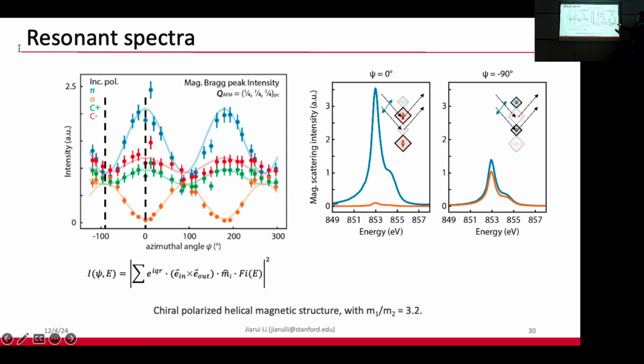So for example, at this position with a pi polarization, we can enhance the spin-photon interactions in these orange clusters. But if we switch the polarizations, we're suppressing those half of the spin sites, but enhancing the other spin sites. And as we scan the energy across these nickel resonances, the spectral shape tells us what the magnetic scattering form factor is, or you can relate it to what the electronic structure of the spins is.